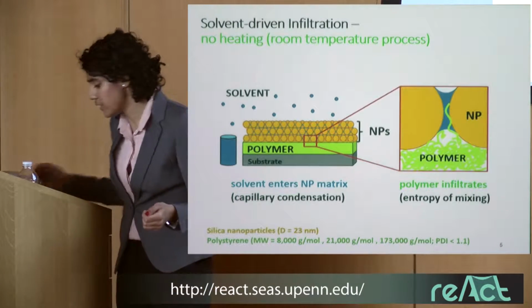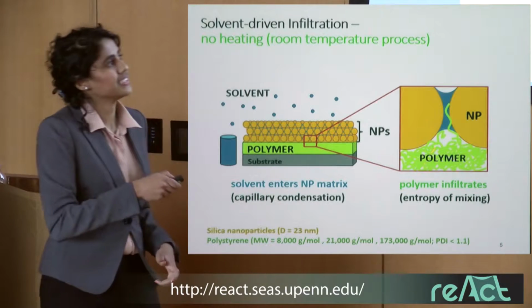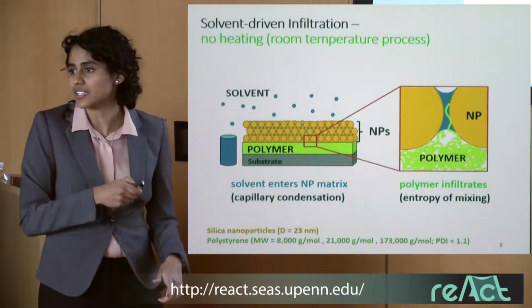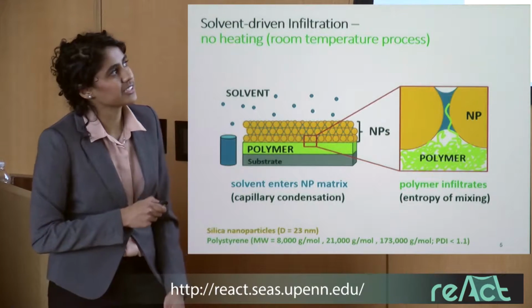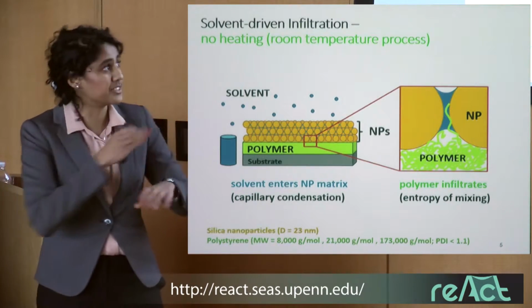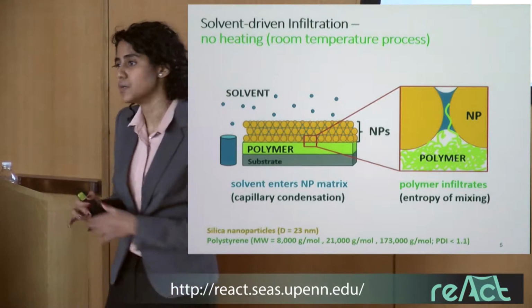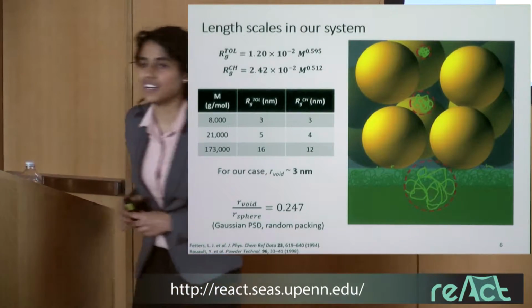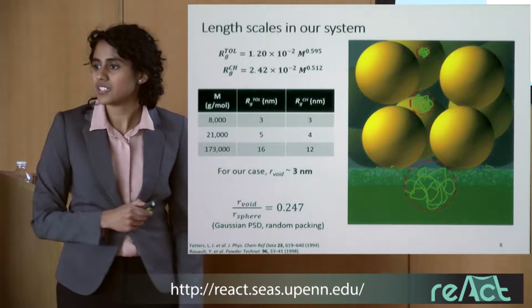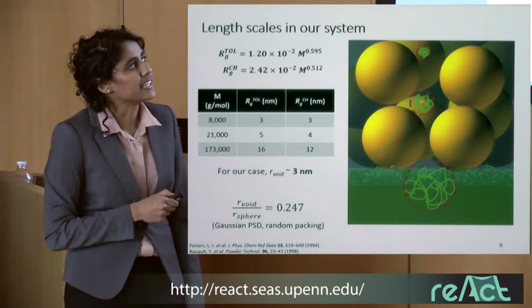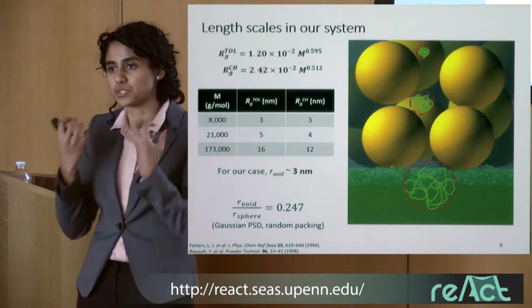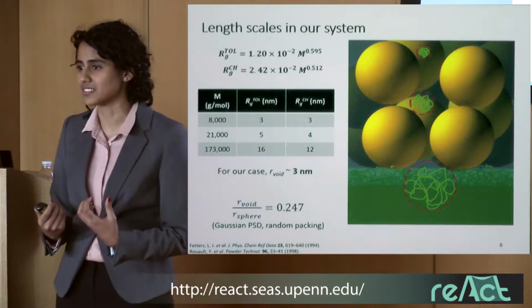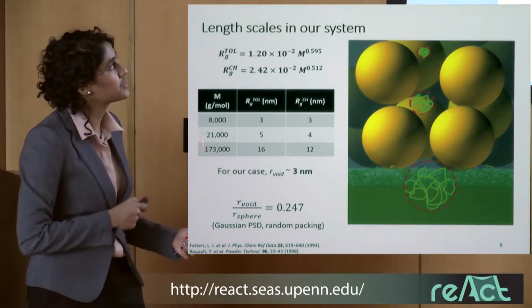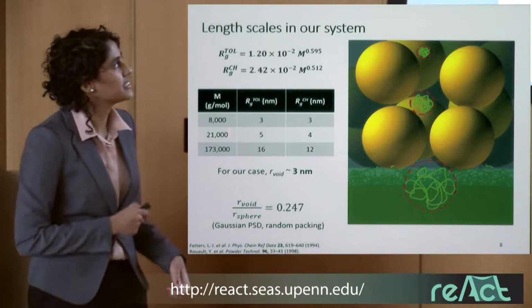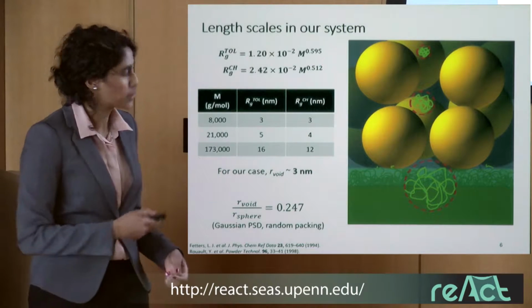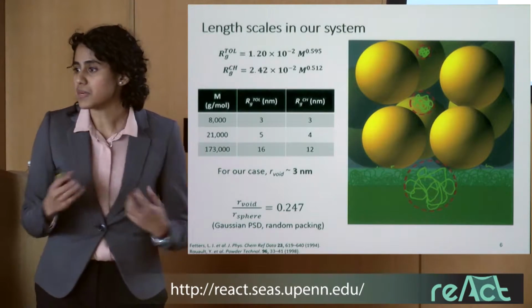So what happens then is we hope that we can induce the polymer to infiltrate just by an entropy of mixing driving force. And you can see here's the really high negative curvature of this fluid interface that leads to the stabilized liquid state. So in my system, if you look at it, the length scales of my polymer in the solvent phase in the dissolved state are actually very comparable to the void spaces between my nanoparticles. So this is a very highly confined system. And I used 3 different molecular weights of polymers, and you can see that the size scaling of the radius of gyration is quite comparable to the average void fraction in my nanoparticle packing.